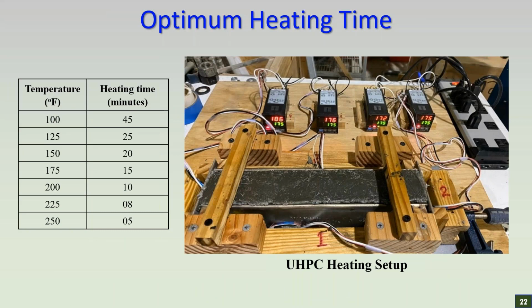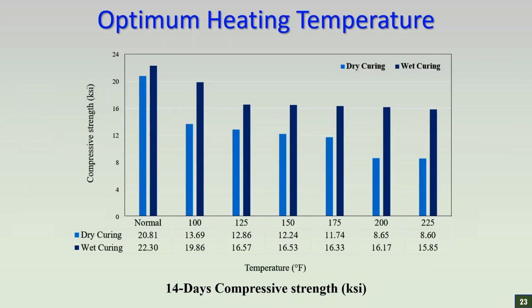When we heat the material, it becomes very important to optimize the heating time. To do so, a simple setup was prepared using a strip heater, shown here, and the material was heated at different temperatures to select the heating time on the basis of shape stability and shape retention. It is shown that if we heat the material up to 100 Fahrenheit, the open time is quite high, approximately 45 minutes. As we increase the temperature, the open time reduces. For 250 Fahrenheit, it can go down to only 5 minutes.